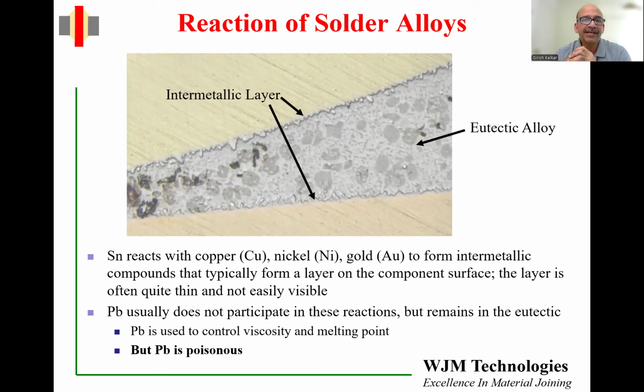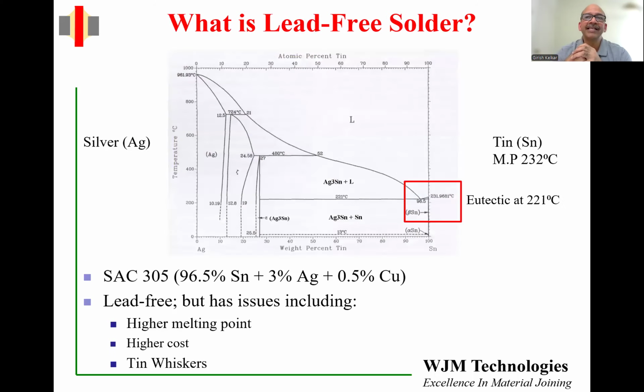So a lot of rules have now come into place. Again, these rules have been there for quite some time, where for many applications we are now using what is called lead-free solder. So what exactly is a lead-free solder? Obviously, as the name implies, there is no lead in this solder. So here I'm showing you a phase diagram. This is between silver and tin. The left axis is temperature and silver. If you start from room temperature and heat it up, silver will melt at 961 degrees centigrade. On the right-hand side, the tin will melt at 232 degrees centigrade.